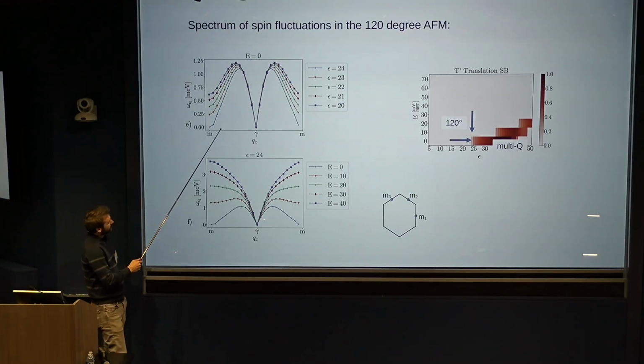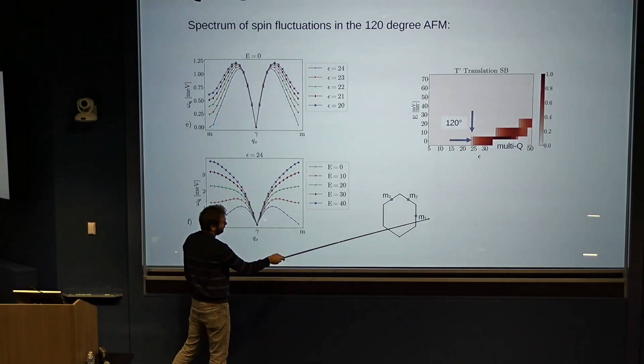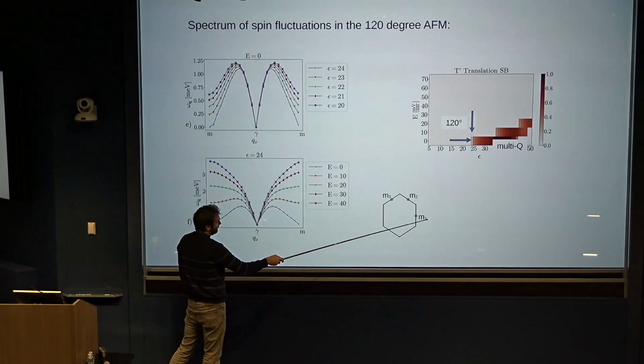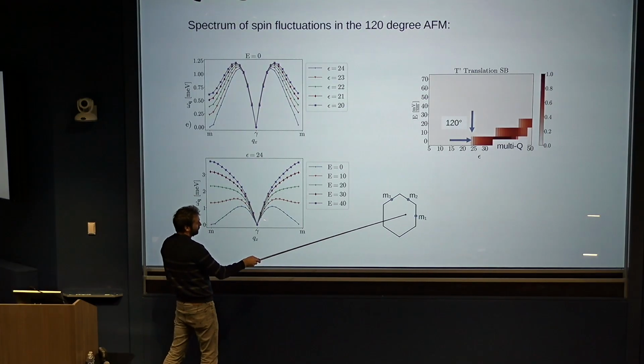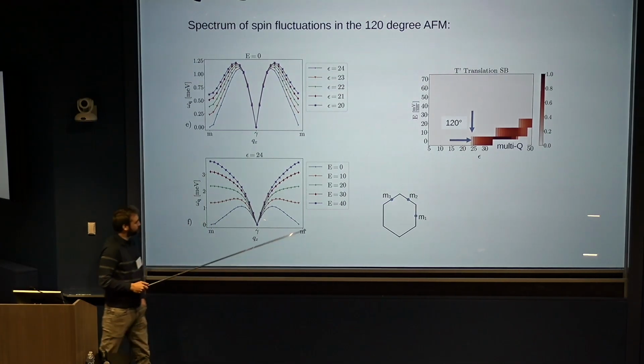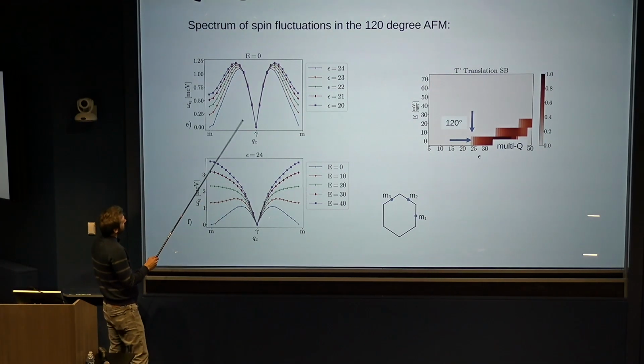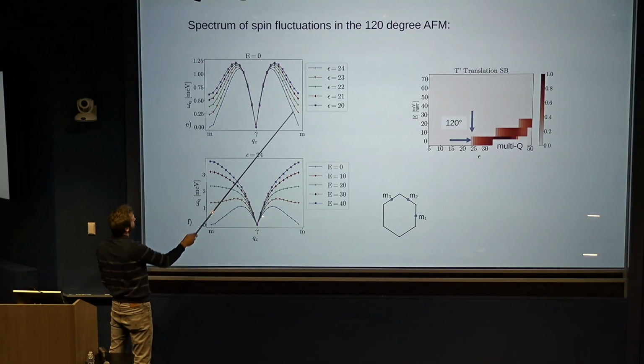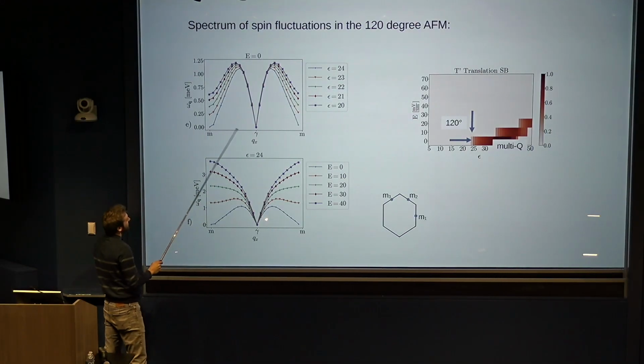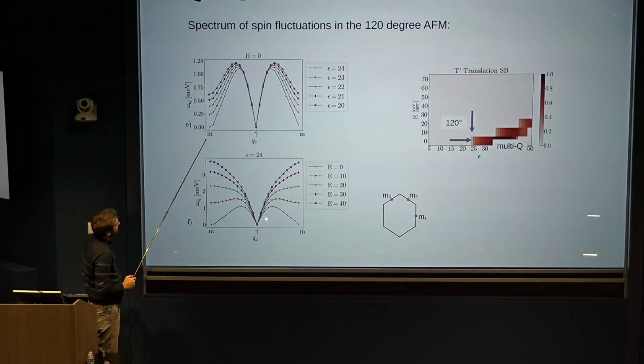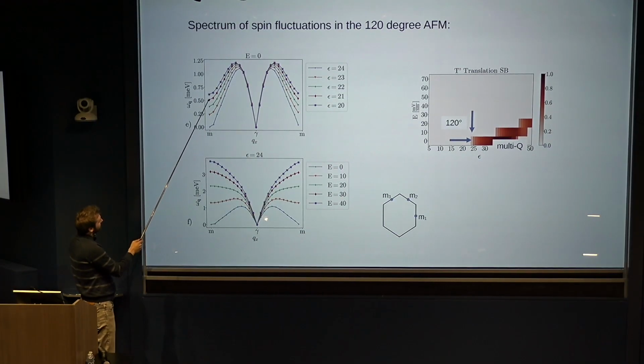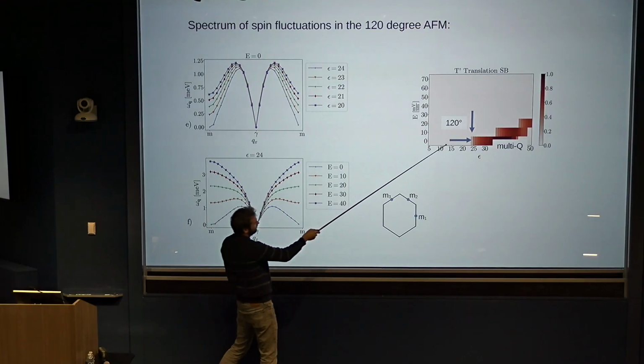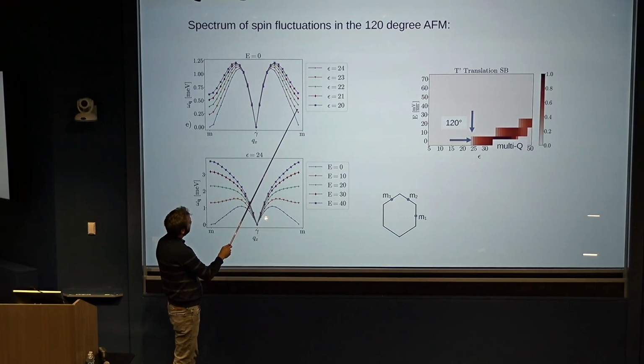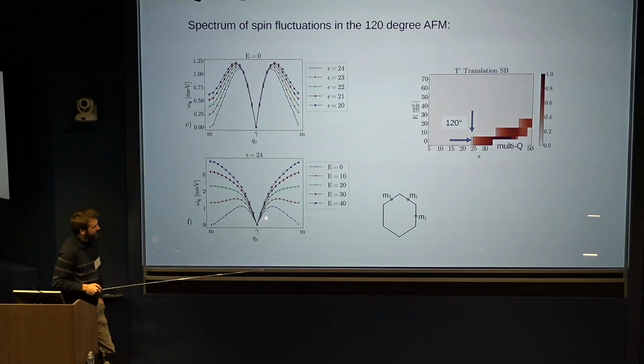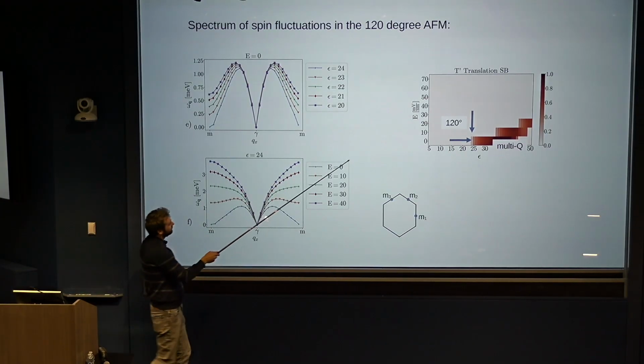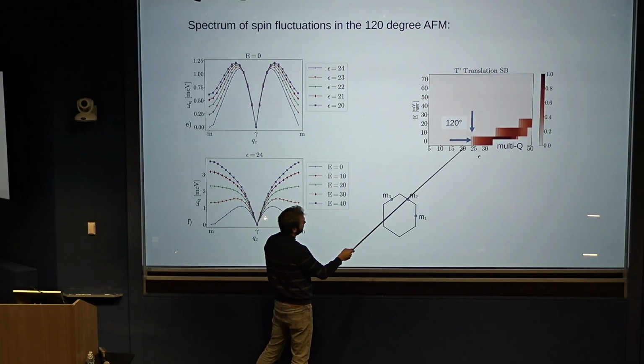So what I'm plotting here is a cut through the mini-Brillouin zone, or the Moiré-Brillouin zone, basically along the x-axis, so it cuts through the gamma point and this endpoint here. And you see here, this is the spectrum of the spin fluctuations, of the magnons, basically. And you indeed see that at the endpoint, as I approach this transition here, there's a softening of the spin fluctuations. So this is at fixed displacement field, increasing dielectric constant.